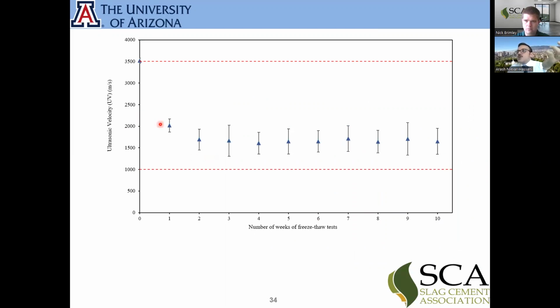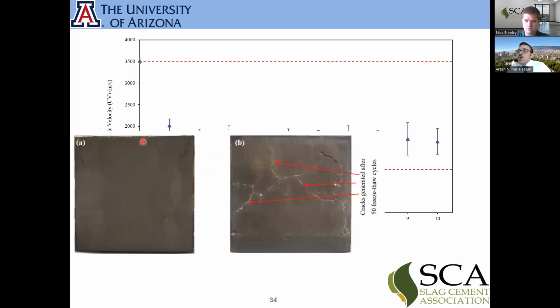The ultrasonic velocity testing showed that the velocity of the wave passing through the sample is not changing much during the freeze and thaw test. That means there is no major cracking developing inside your samples. There are only a few minor cracks on the surface of the samples, and they don't affect the integrity of your sample.